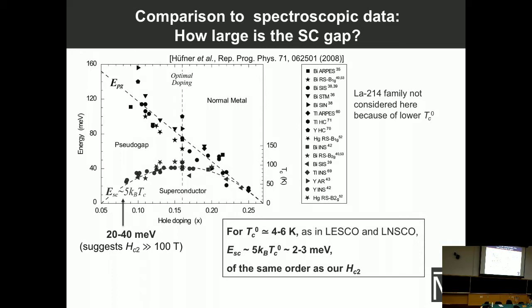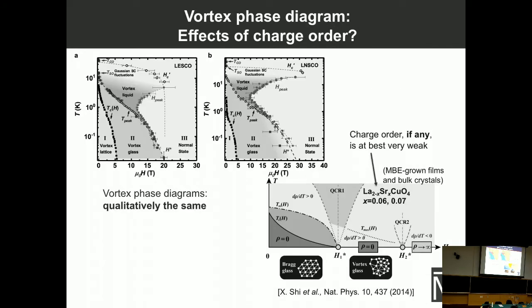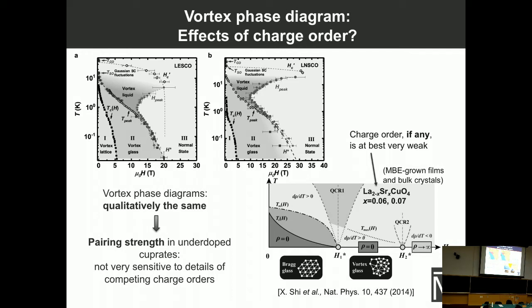So finally, what are the effects of charge order? As I said, these two materials have a different strength of stripe correlations. The stripes are stronger here, but the vortex phase diagrams, which is what we studied, are qualitatively the same. And in fact, qualitatively the same result was found in very underdoped LSCO, in which charge order has not been found yet, although people have looked, and if there is any, then it must be very weak. So we see that the pairing strength in underdoped cuprates is not very sensitive to the details of these competing charge orders, although the precise values may depend on that.